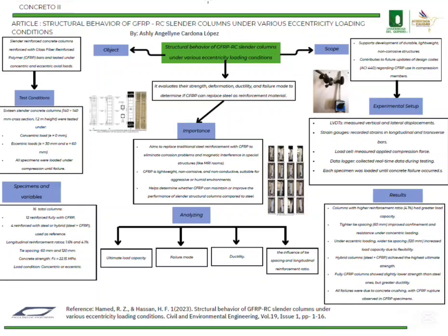From all of these results, several important conclusions can be drawn. GFRP is a viable alternative to steel reinforcement, especially in aggressive environments where corrosion is a major concern. The behavior of slender columns strongly depends on both the type of reinforcement and the loading conditions. Hybrid columns combining steel and GFRP showed the best overall performance, while GFRP-only columns still exhibited competitive strength and better ductility. The reinforcement ratio and tie spacing are critical design variables that control the load capacity and failure mode.